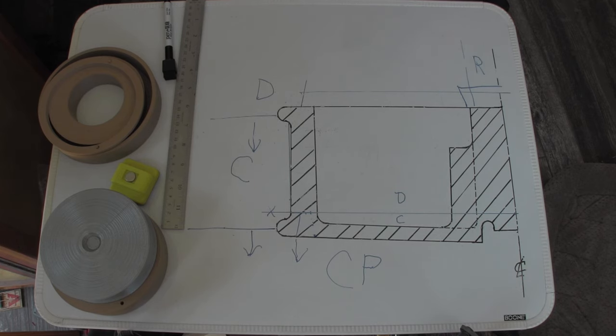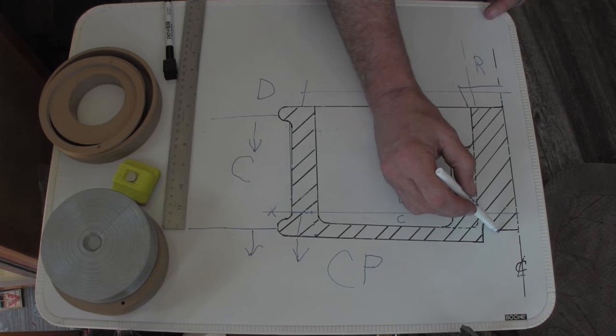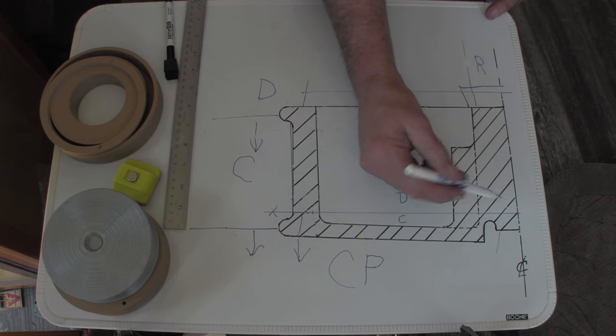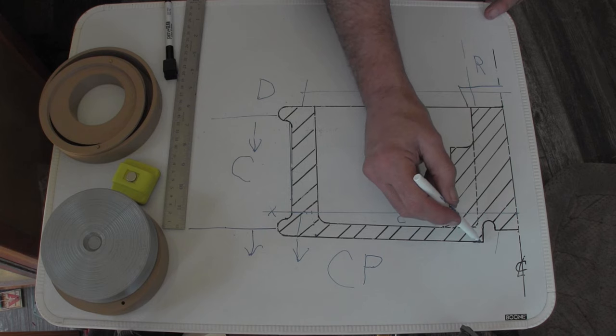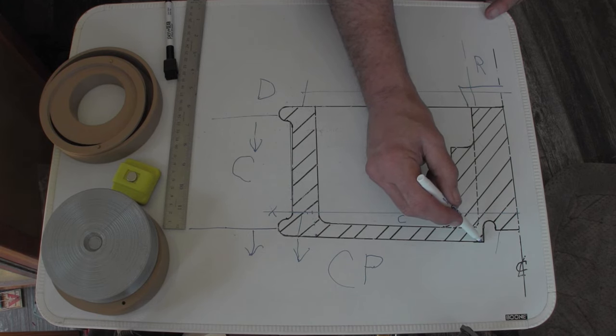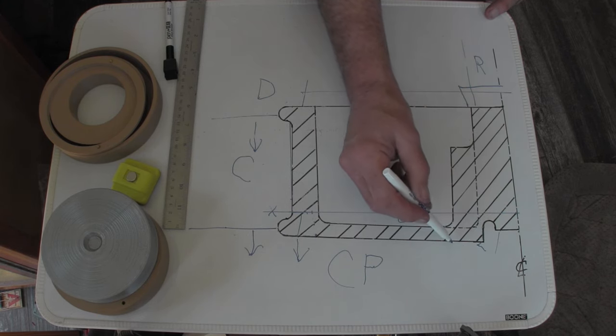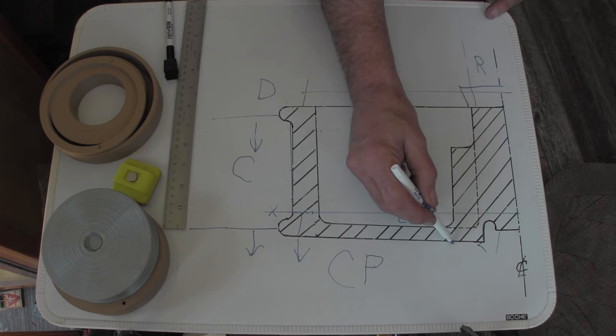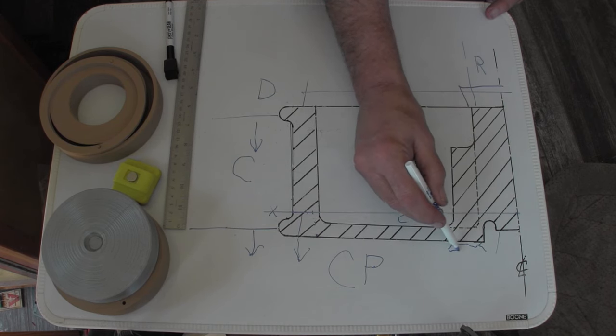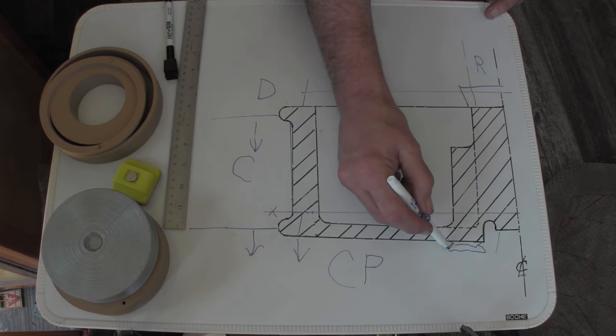And if you make your core print deep enough here, you can actually put it in the core print itself, and it wouldn't be a big deal. Everything would work just fine. The chill, you could then, if you need to, either add a riser here, which would be hard to cut off, or you could add what we called a riser here. It's a knockoff core, would be here, and that way, and then the riser would be here.